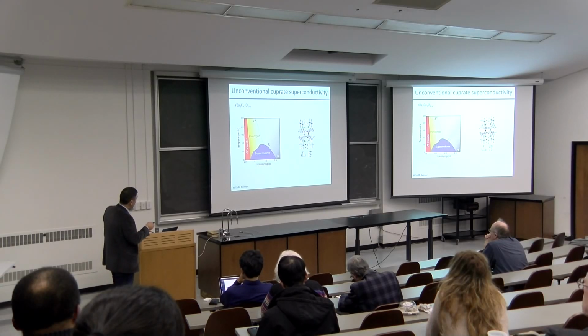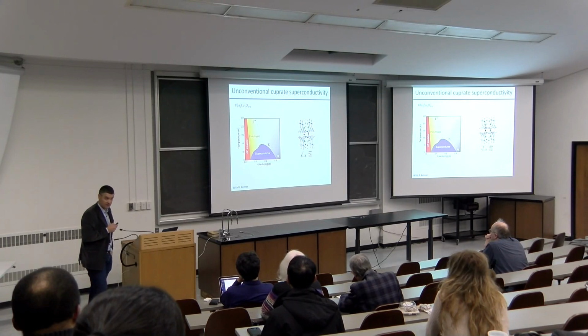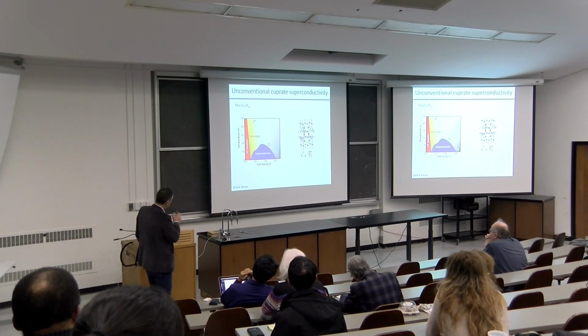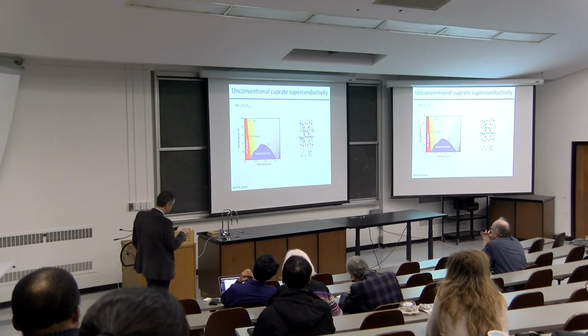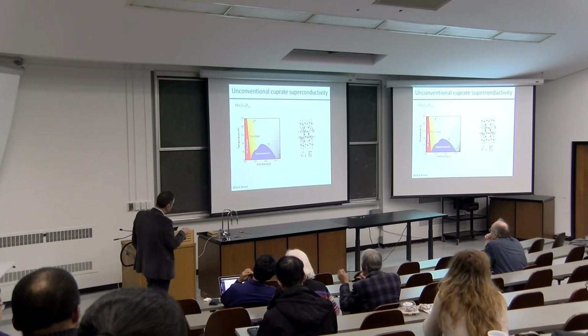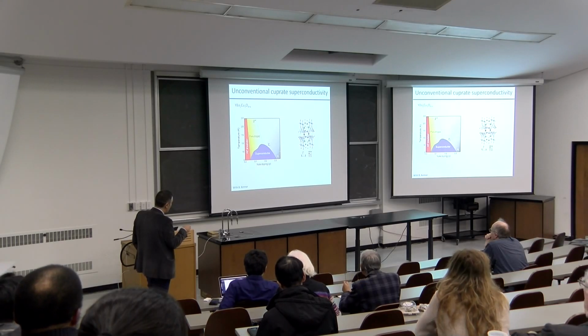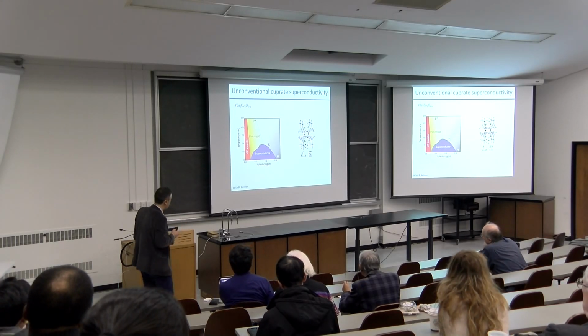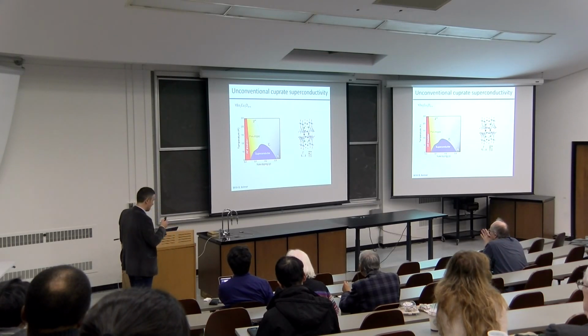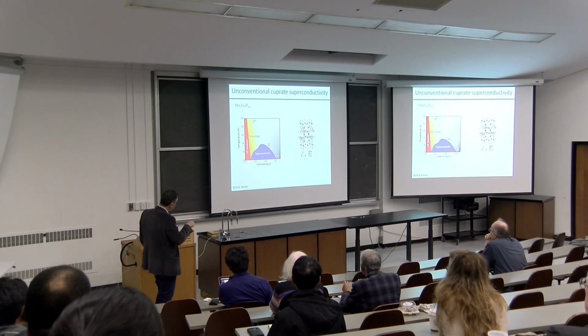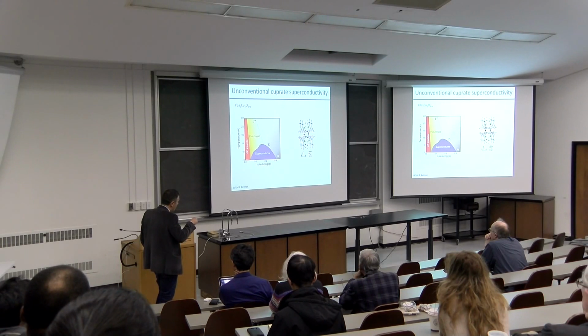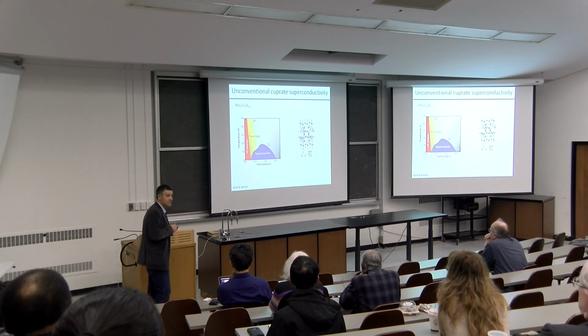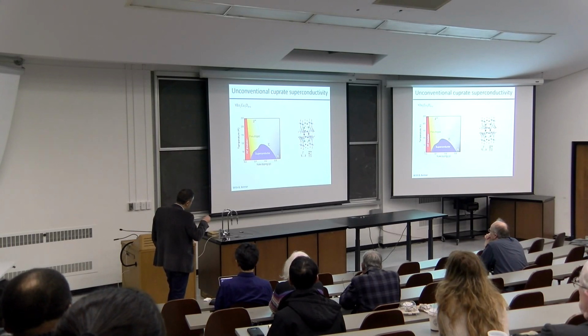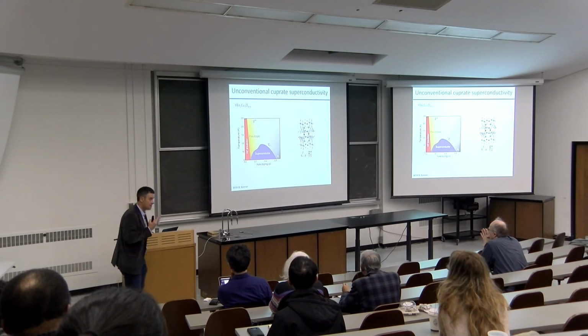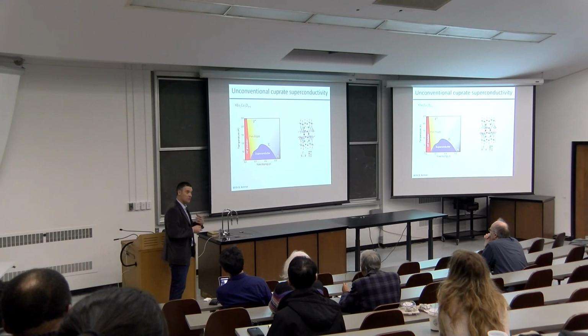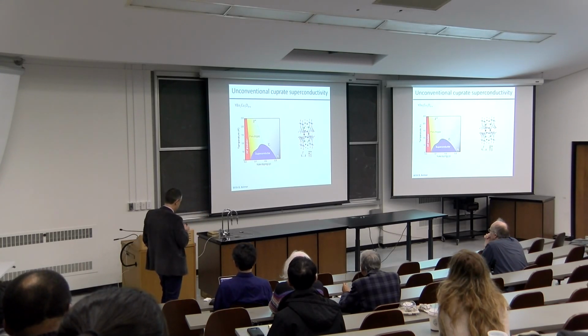This is a plot of yttrium barium cuprate. It's a 90 Kelvin superconductor. It's a bilayer compound, and this is one of the many incarnations of the phase diagram of this material. So what one can do is change the doping of holes in the plane of this material, and what one finds, this is one of the great surprises of the late 80s that generated at least one Nobel Prize, is that if you put between, say, 5% holes and 25% holes, one finds superconductivity at basically room temperature divided by 3. So this is a ceramic which creates an unprecedented scale for superconductivity.